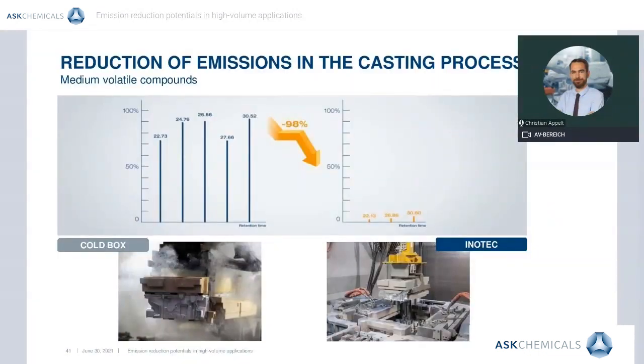The 100% emission-free footprint of the Inotec technology can vividly be demonstrated best by comparing the formation of fumes and smoke as a result of the thermal pyrolysis of the binder system upon casting or at the raw part in the process of permanent die mold ejection. The left picture shows a polyurethane standard cold box bound core package after cylinder head casting directly at the ejection process of the permanent die mold. The formation of pyrolysis products visible by fumes and smoke leads to the necessity to implement exhaust air treatment systems.